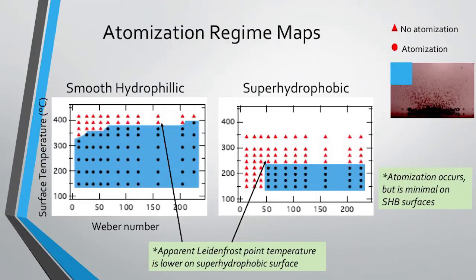This is just a quick map. If you look at Weber number versus the surface temperature, the blue is the region where we actually get atomization. And you can see when I have a smooth hydrophilic surface, I'll get atomization up to 350, 400 degrees C. Whereas on a superhydrophobic surface, I get a little bit of atomization in this region. So for varying Weber numbers, so how fast basically I allow the droplet to hit, up to about 225 degrees C, but that's about it, and it's just very little.